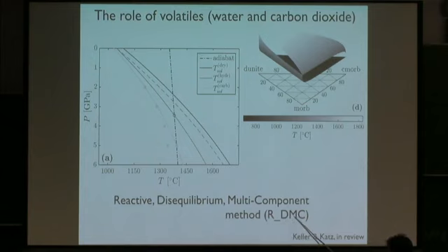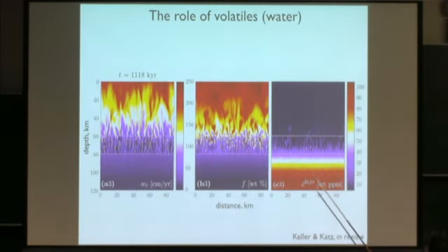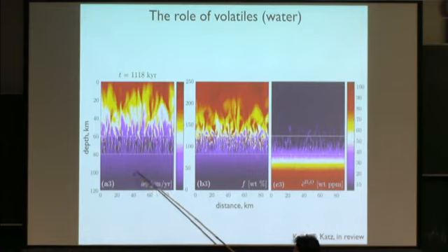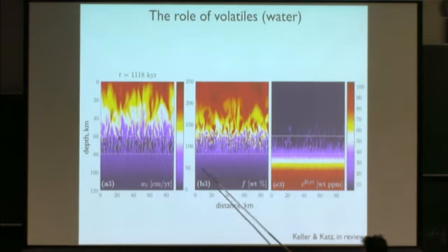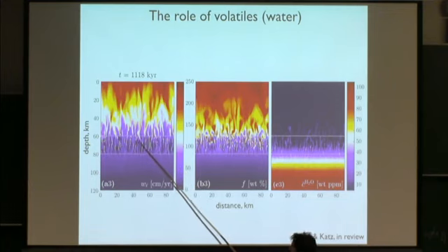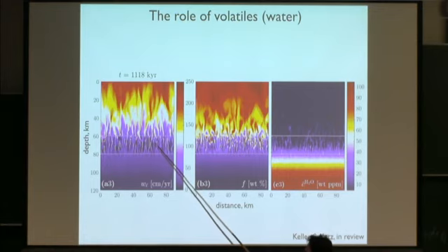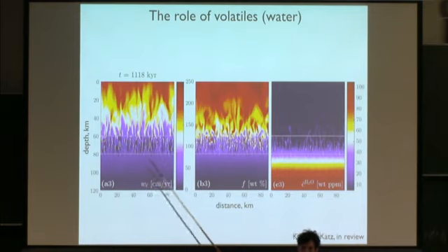So reactive disequilibrium multi-component, with an underscore, and for fun we like to call it Run DMC. So the Run DMC model is underlying the calculations that I'm showing you next. This is the role of volatiles, and in particular here this is water. So mantle upwells, begins to melt at the hydrated solidus, and then as you approach the depths where you transition from water-rich melting to silicate melting, there's a very strong channelization for the same basic reasons that we saw in the previous calculations. There's a corrosive reaction going on that is leading to enhanced melting where the flux is greater. And so you get this strong channelization, and then it kind of fades out.